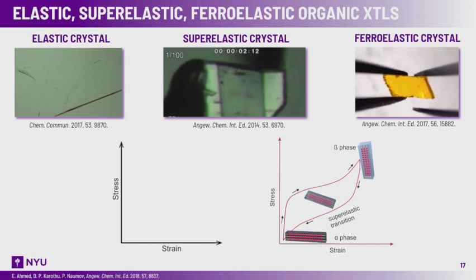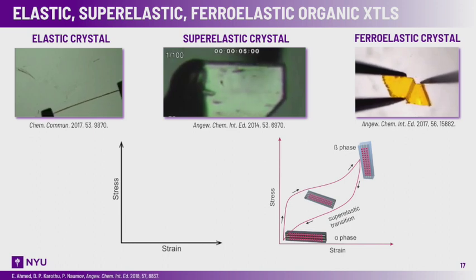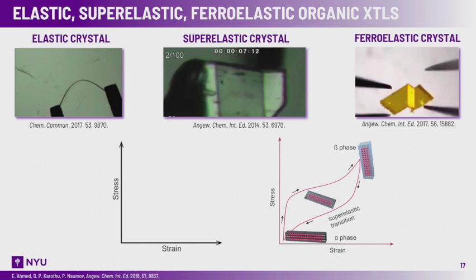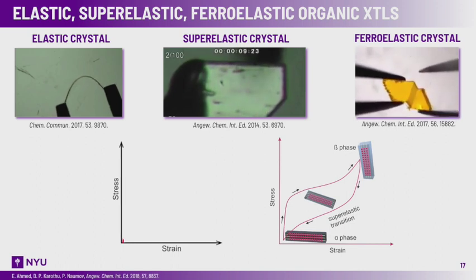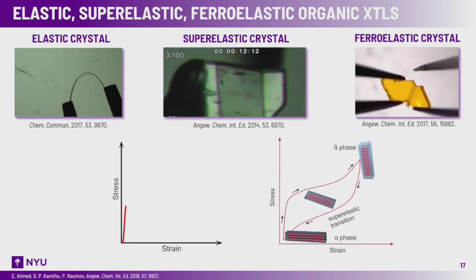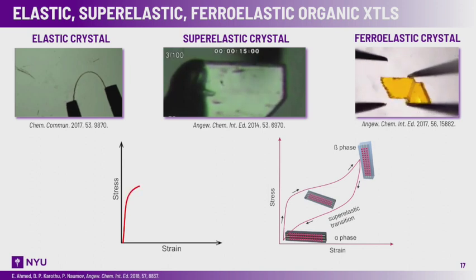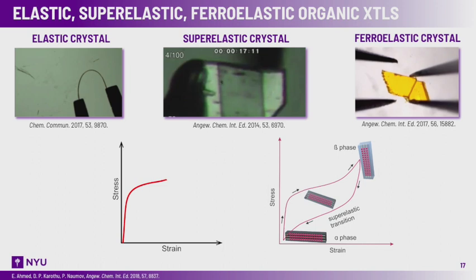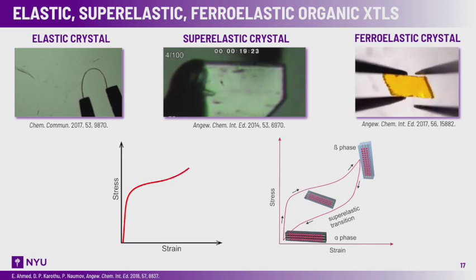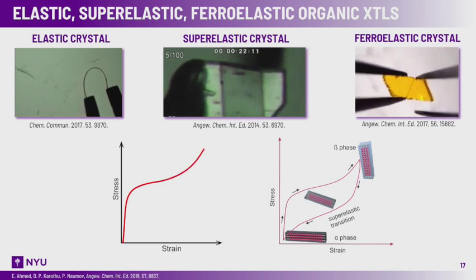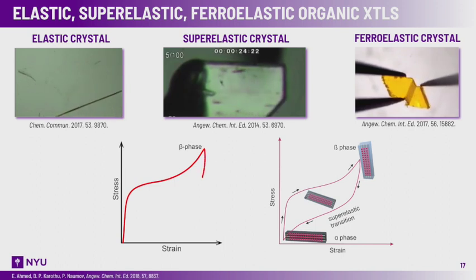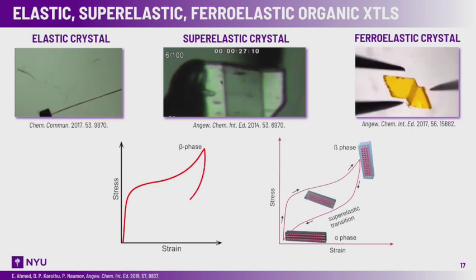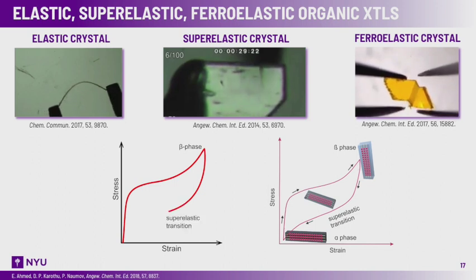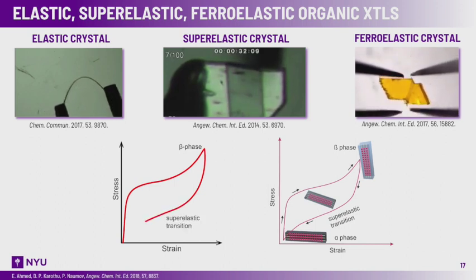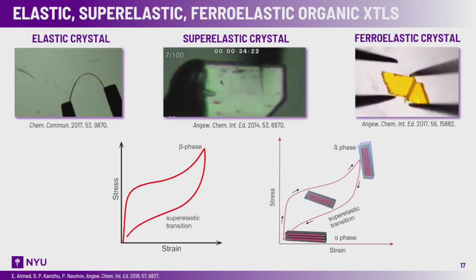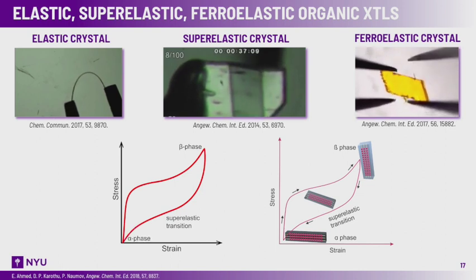There is also interesting research developing around superelastic organic crystals. Probably you are familiar with the concept in other materials. In the elastic regime, when you apply a stress to a crystal, it goes through a linear stress-strain regime, which we can use to calculate the Young's modulus. But if the application of stress is coupled to a phase transition, the crystal can sustain a much larger strain for the same amount of stress. So instead of, let's say, 2%, we go to about 12% strain.